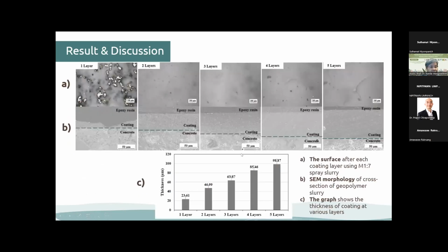In the experiment, the slurry of specimen M1:7 was sprayed on the substrate. This formulation was then selected to investigate the thickness of the coating layer. In the first coating, as shown in the picture, there were areas of non-uniform thickness due to insufficient coating. After the second and third coatings, the surface became smoother with no visible cracks due to sufficient coating.